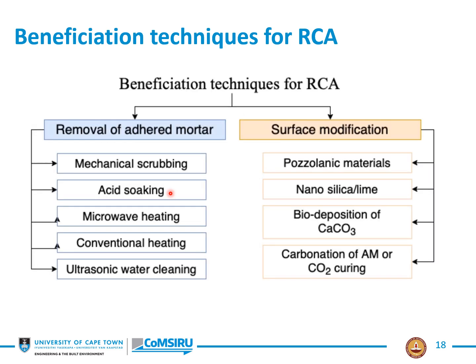So here are these first 2 strategies, the removal of adhered mortar or surface modification. In the first case, one can do mechanical scrubbing, acid soaking, not a particularly good idea, microwave heating, conventional heating, or possibly ultrasonic water cleaning. That's also not a very useful idea. On the surface modification side, one can add pozzolanic materials to try and utilize some pozzolanic reactions, the possibility of adding nano materials, biodeposition or carbonation. This is more the mineralization route, which I'm not going to speak about now.